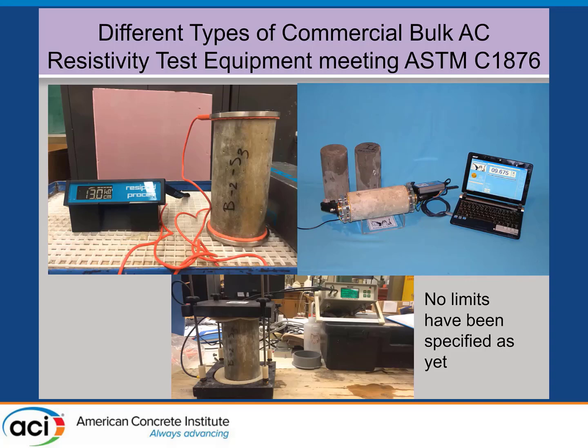It's much cheaper. In fact, you can do it on the same cylinders you're going to test for strength, which means you don't have to cast extra specimens. You don't have to cut slices and all that. You can take the cylinder out of the moisture room if the ends are flat or ground flat or sliced, and you measure the resistivity, then you can cap it or whatever, however you're prepping the ends, and test strength.